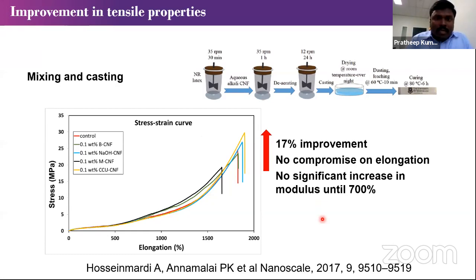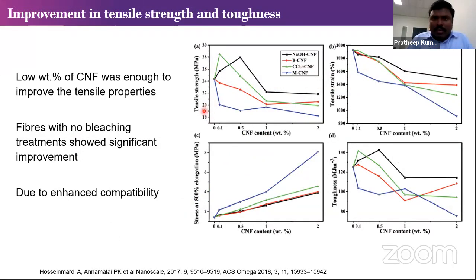Compared with the other properties, we can see that this is achieved at a really low volume percentage of cellulose. You can see the black line and green line, within 0.5% loading levels. We can also see that the toughness, which is the energy required to break this material, is also increased from the control, within 0.5% of nanocellulose.